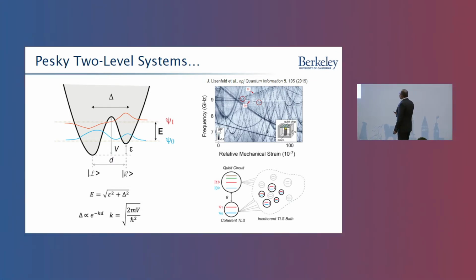And in particular, I want to pay homage to this very beautiful experiment of Professor Ustinov, who's here and will be speaking later, where these two-level systems are thought to have both an electronic component, so they couple electronically to your qubit, but if they're structural, they should also couple to the strain field. Typically, we don't have a handle on the two-level system. We're measuring electronically these superconducting circuits. But in this experiment, they literally put, figuratively and literally, a screw on the problem to add strain to the system and actually sweep the two-level system. The spectroscopy of that is exceptionally rich, beautiful, or messy, depending on which side of the problem you want to look at. There are a lot of two-level systems, and they even interact with each other.